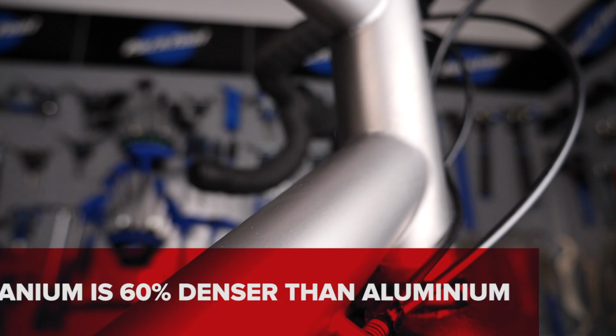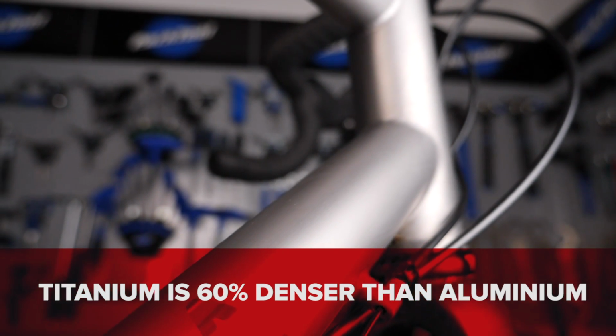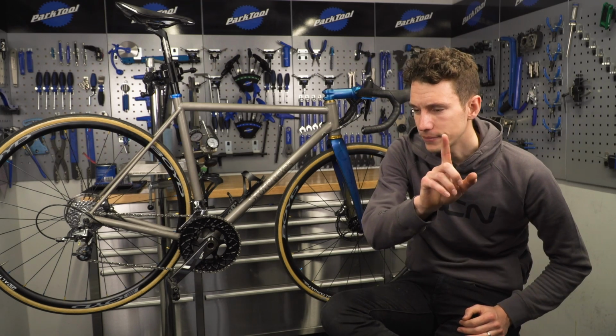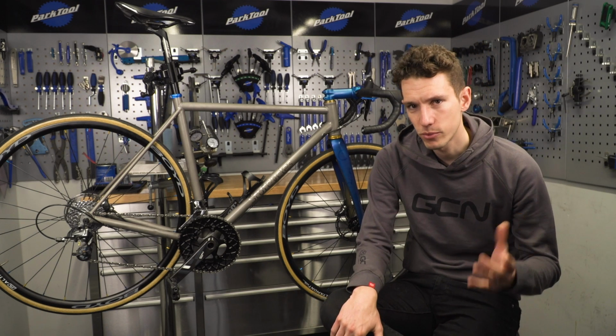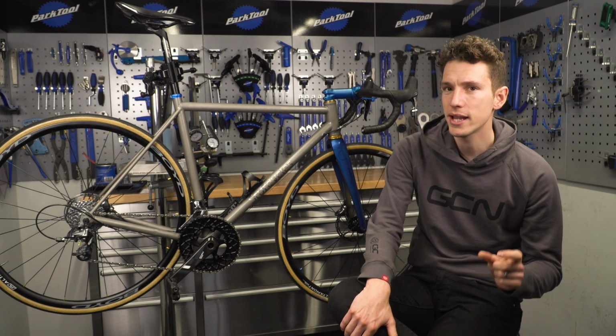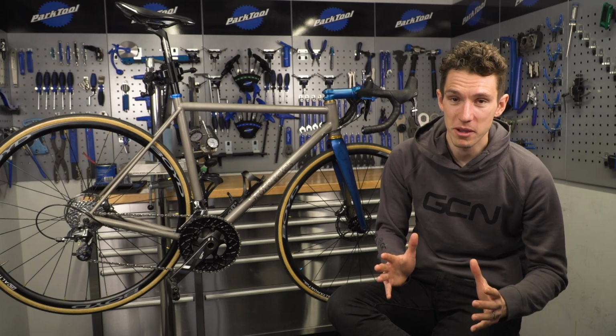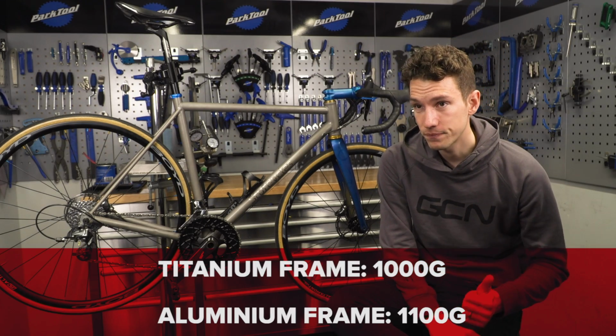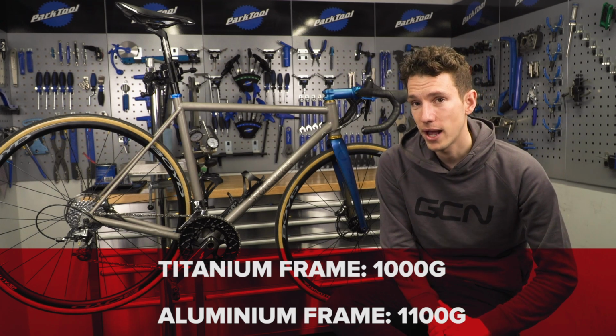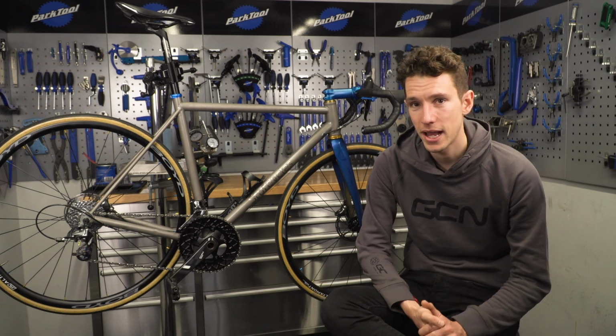Titanium is renowned as being super light, but in fact, as a material, it's actually 60% denser than aluminium. However, given what we've just heard about the other material properties, you can still see why titanium frames tend to come out slightly lighter than aluminium ones. So the best examples of each would be about 1,000 grams for a titanium frame and about 1,100 grams for aluminium. So 100 grams in it.